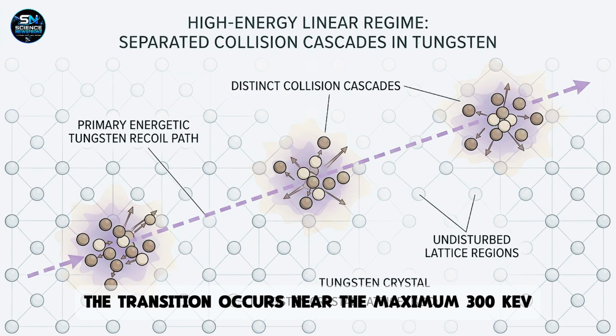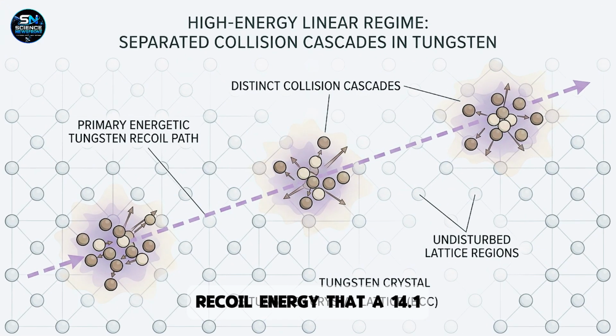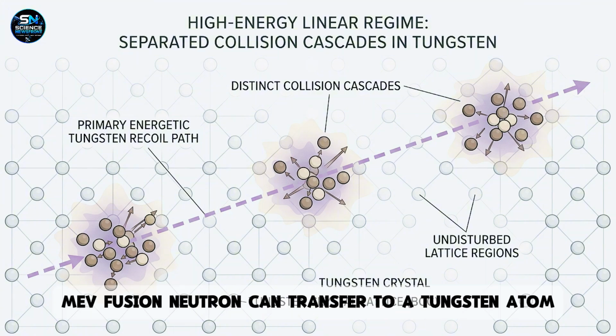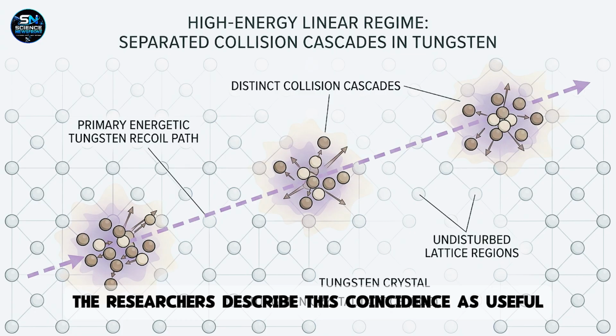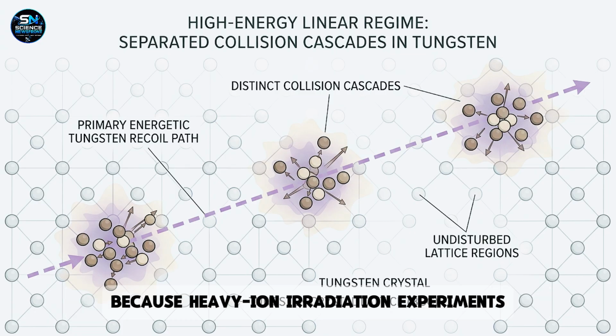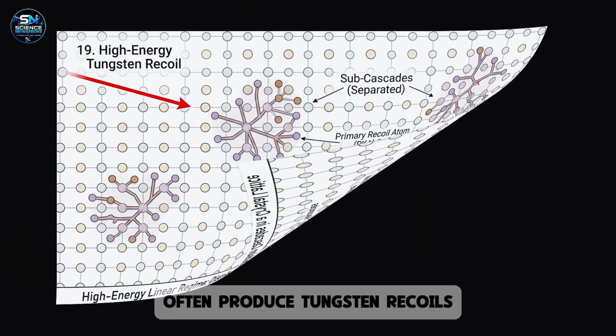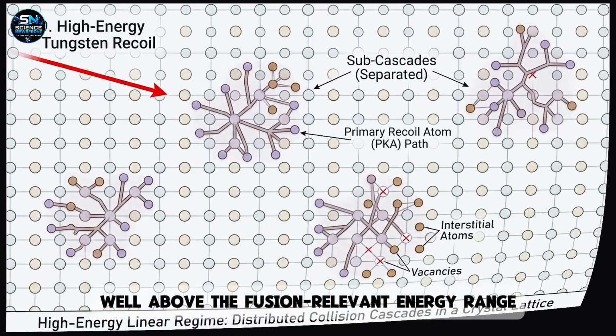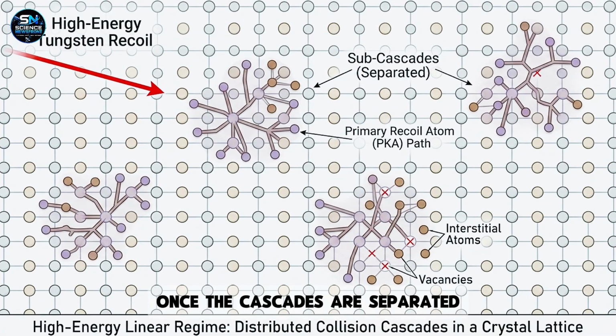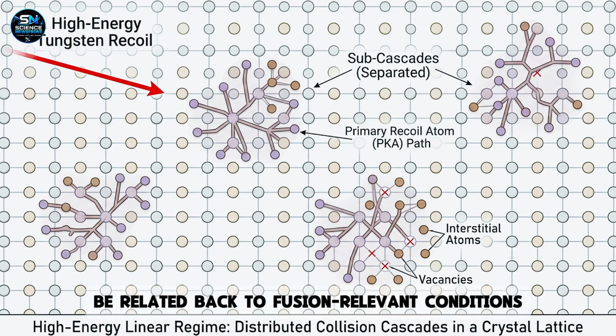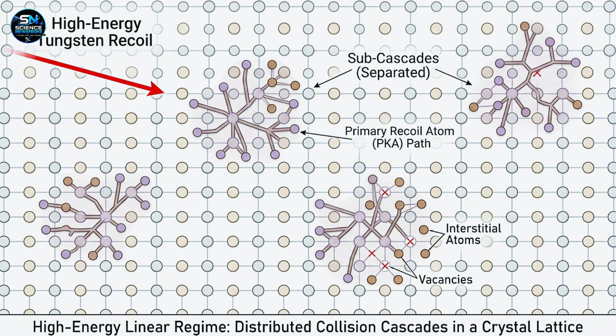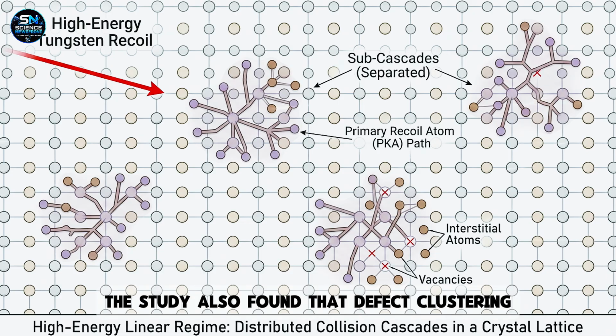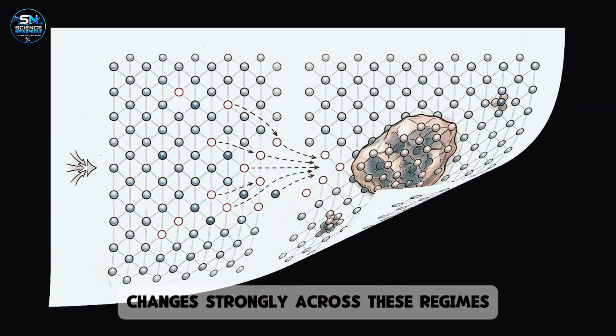Significantly, the transition occurs near the maximum 300 keV recoil energy that a 14.1 MeV fusion neutron can transfer to a tungsten atom. The researchers describe this coincidence as useful because heavy ion irradiation experiments often produce tungsten recoils well above the fusion-relevant energy range. Once the cascades are separated, their effects can potentially be related back to fusion-relevant conditions through the newly quantified linear scaling. The study also found that defect clustering changes strongly across these regimes.